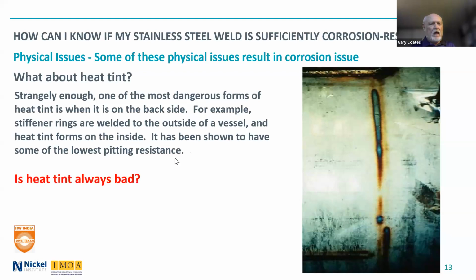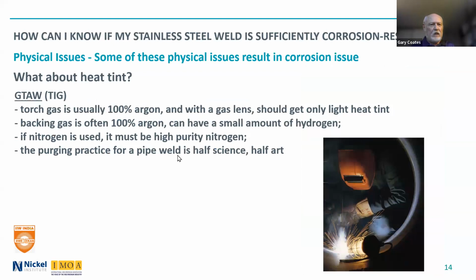Is heat tint always bad? Well, that's a good question. Well, let's talk about the formation of heat tint. So with gas tungsten arc welding or TIG welding, usually the torch gas is 100% argon, especially if you have a gas lens so the flow of the argon is not turbulent. You should only get a very light heat tint. The backing gas, most often 100% argon. Sometimes for critical applications, it can have a little bit of hydrogen in it.